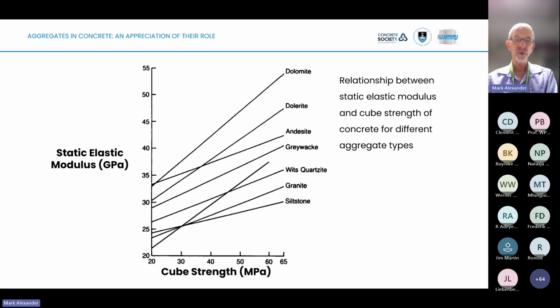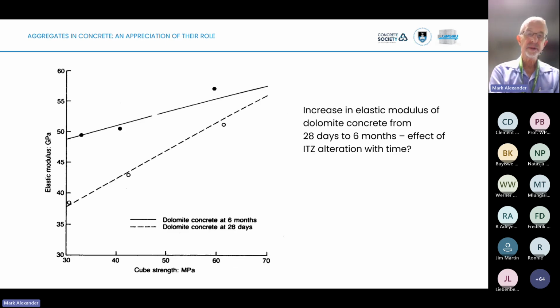And here's an even more interesting one, where taking the dolomite concrete and looking at the difference between the 28-day values of strength versus elastic modulus, which is given here in the dashed line, versus the solid line, the same concrete if we allow it to mature for 6 months, you can see the vast difference. So, for example, more at the lower strengths, you can see that we can again push that modulus up from under 40 to close to 50, by maybe 10 gigapascal.